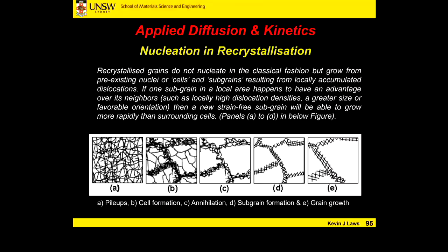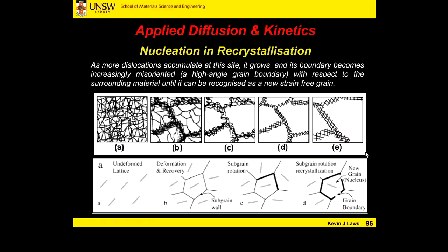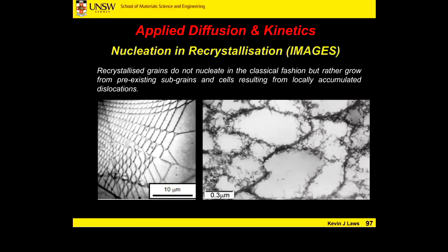We then had a little bit of a look at the actual mechanism for the formation of new grains, and how the nucleation of new grains is driven by deformation, and by the entanglement and localization and formation of dislocation cells in our material. Our dislocations that are a result of deformation start to form cells within the material, and within those cells our dislocations are essentially annihilated, and these will become new grain boundaries under the correct conditions. Some examples of dislocation cells in material after deformation.